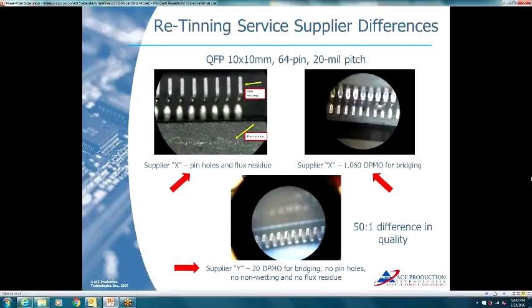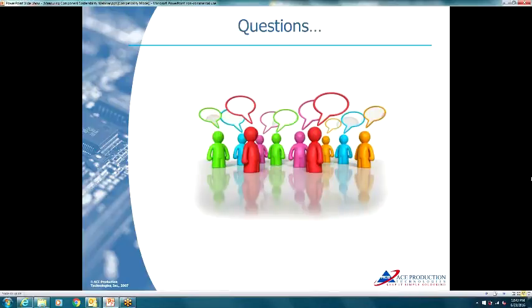What's interesting is there's a difference between retinning suppliers. This is an example. This is a 64-pin, 20 mil pitch QFP that's done in relatively high volume, let's say 1,000 plus per week on an ongoing basis, and you can see the difference between two different tinning service suppliers. One has pinholes and residues, and you can see a significant difference in defects per million opportunities in bridging between the two suppliers. And that's it, Bob.